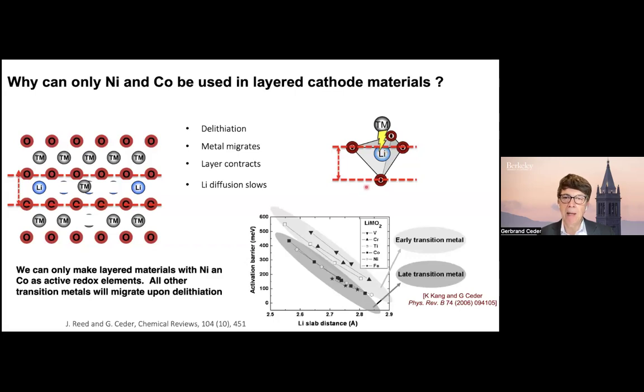And now you see why the slab spacing matters. The slab spacing actually sets the size of this tetrahedron. So if the slab spacing is very large, then the lithium can stay far away from the transition metal. If the slab spacing gets contracted, then lithium will not want to hop through that tetrahedral site. And that's why if you look at the lithium diffusivity in layered materials, it essentially follows the slab spacing. When the slab spacing is high, the lithium mobility is very high. At the end of charge, when the slab spacing contracts, the lithium diffusivity collapses as well.